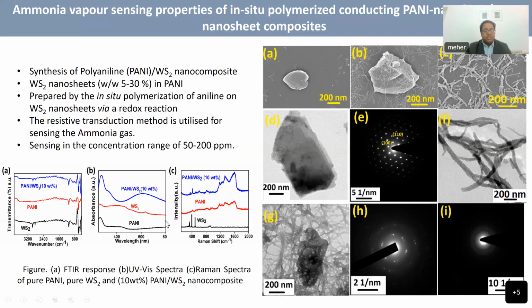You can see here, with the help of different characterization techniques, we confirmed the synthesis of polyaniline nanofibers and tungsten disulfide. Also, you can see the Raman peaks here, which correspond to tungsten disulfide, and this is multi-layered tungsten disulfide. It is confirmed by transmission electron microscopy also that this is multi-layered, and then there are other functional groups we can see from the FTIR and UV.